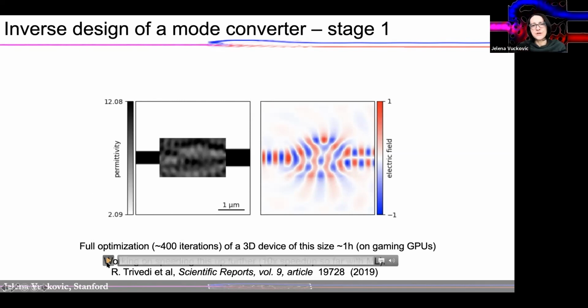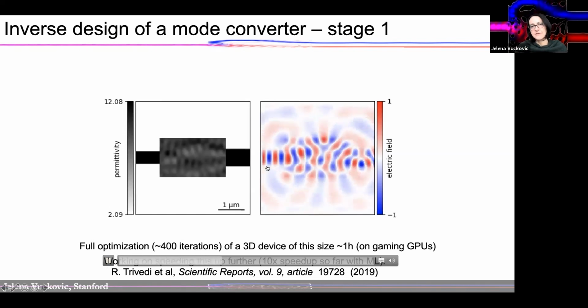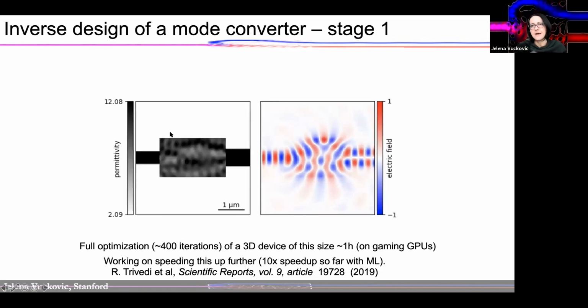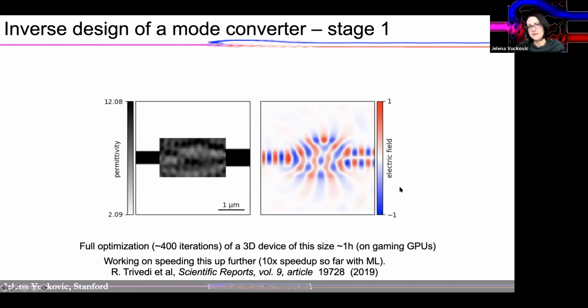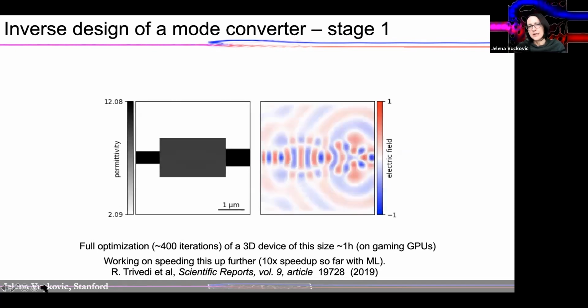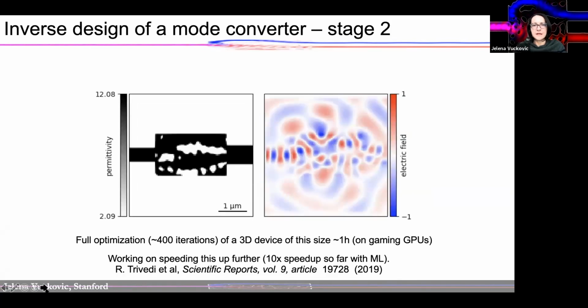So here you see the first phase of optimization, which is just where you allow your refractive index to vary continuously between limiting values, in this case silicon, which is black, and air, which is white. And then you end up with a solution for the electromagnetic field on the right. But that, of course, is not something that you can fabricate. So then you go to the second phase of optimization, which we refer to as the binary optimization, where you design something that you can fabricate and that incorporates constraints and everything.